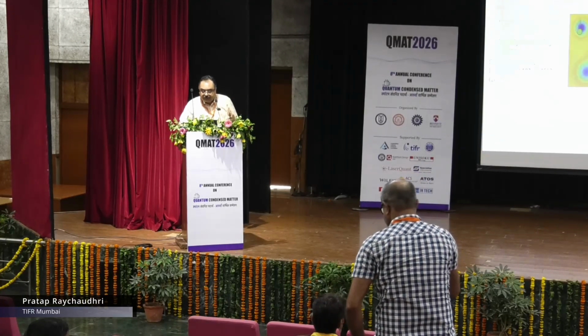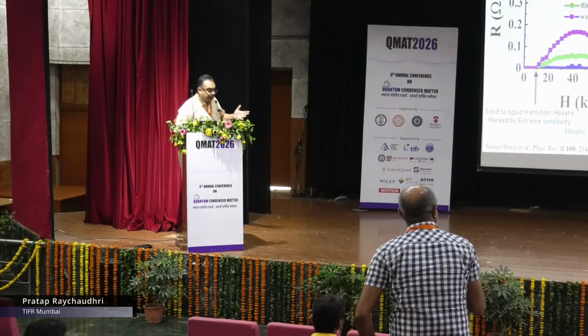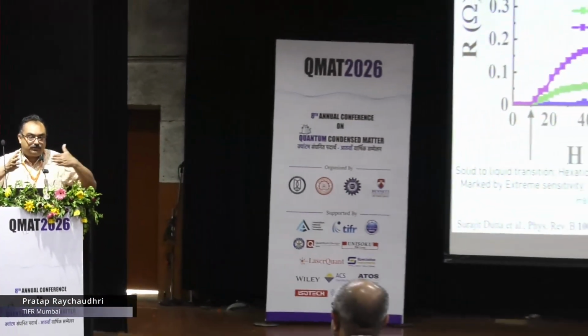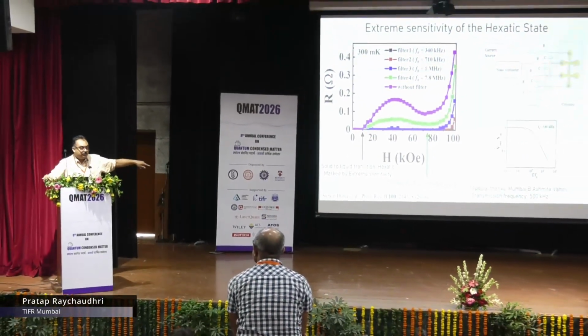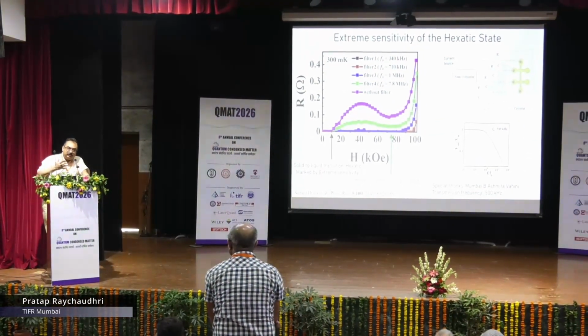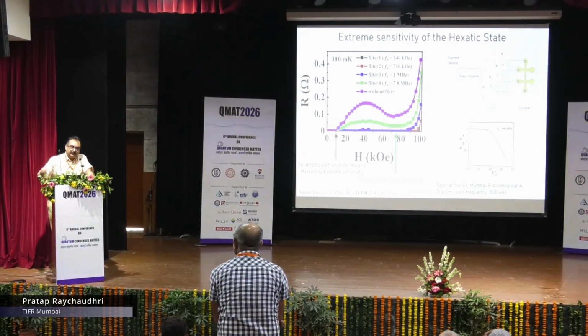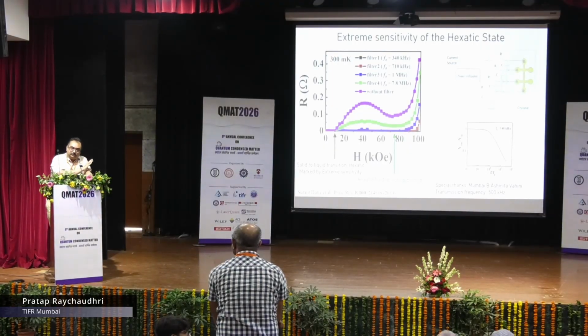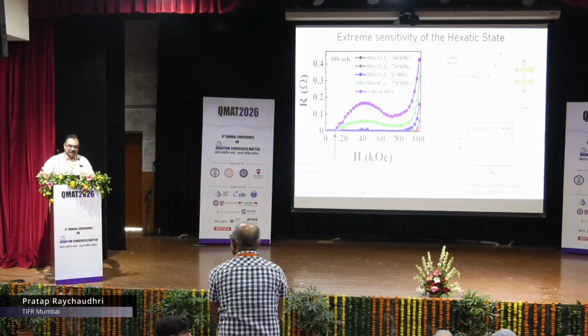As I have shown, this is not something I could show in great detail, but you can already see here that we have these transport measurements, not STM measurements, where you can clearly see first the onset of resistance when you have excitation on the system, where you have a transition from solid to hexatic. Then when the second transition happens, you suddenly have this fluid which was constrained to move in a certain direction; now it can move in all directions. So you have this rapid increase in the resistance again. These are signatures from bulk transport, and yes, we have that. In fact, for every phenomenon that we get through STM, this is something that we always look for. This is one of the standard operating procedures in our protocol.